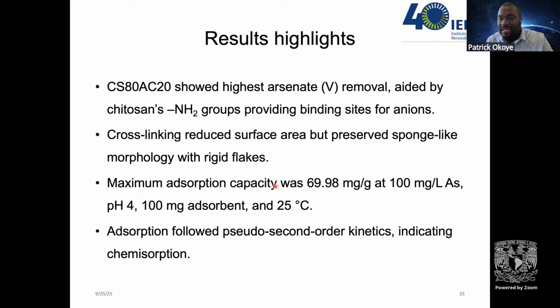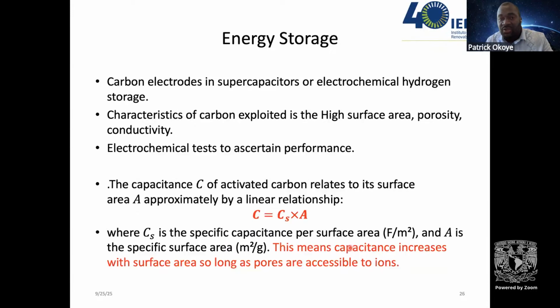whereas our maximum adsorption was about 69.9 at 100 milligrams of adsorbent and 25 degrees. And the adsorption followed pseudo second order kinetics, indicating chemisorption. Now we are done with aqueous phase adsorption and we are going to open a little bit about energy storage systems.